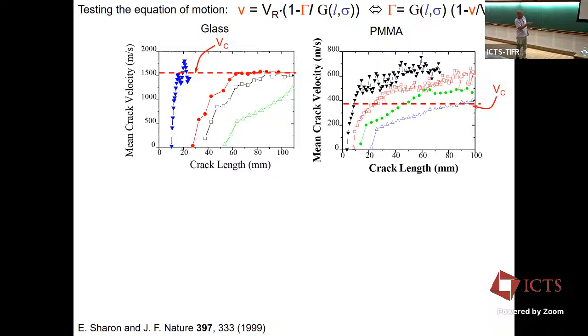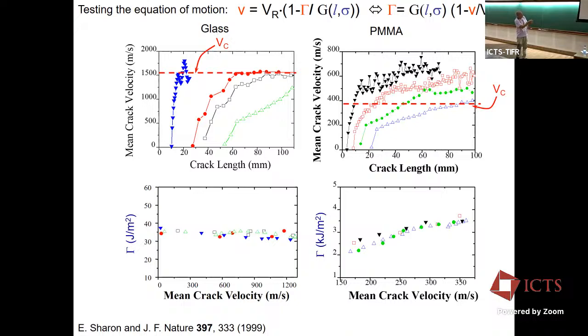The sound speeds, the Rayleigh wave speed is this line here, the dashed line. No, that's not, we'll talk about that in a minute. The Rayleigh wave speeds are up here, and around 400 here for PMMA. And for each one of these, each was initiated at a different stress, and the crack lengths were different, but we could take all of these and use the equation of motion as a filter, and until these dashed lines, we find that we could use this basically to calculate the fracture energy.